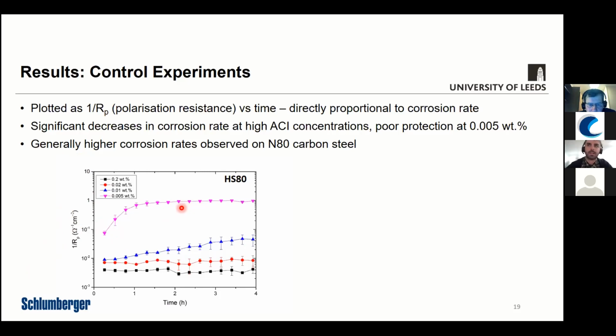But just to give you an idea of how effective the inhibitor has been in terms of corrosion rates you might expect, the pink line here, which is the 0.005 weight percent, so the lowest concentration we studied, essentially gradually tended towards 1. So essentially 1 over an RP value of 1, which becomes essentially the limitation of what we can physically measure with this particular technique, because the currents are so extreme, and the other resistances present in the solution become significant in the measurement. So essentially this 0.005 weight percent inhibitor concentration for HS80 over that test duration provided no real inhibition at all, and the corrosion rates were extremely high.